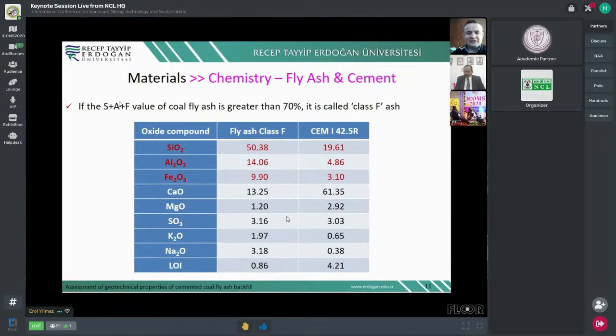There are actually two classifications of fly ash. One is type F. If the silicon dioxide, aluminum and ferrous oxide value of coal fly ash is greater than 70%, it's called type F fly ash. So when you calculate the value of fly ash, you can see that our material belongs to type F. Type F compared to type C produces a lower UCS value, strength value.